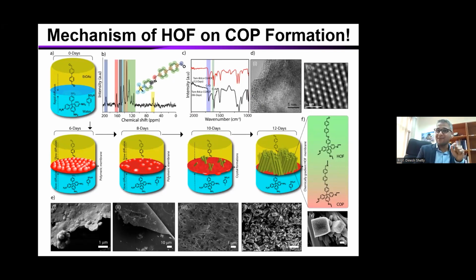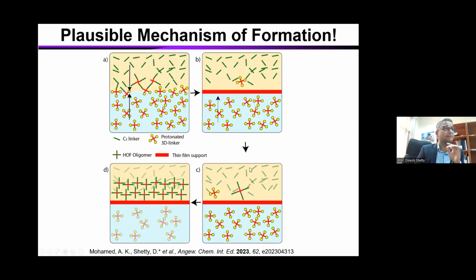But if you think about it, you're talking about the same building block. Usually when we talk about hydrogen bonded networks, right, HOF films, hydrogen bonded organic frameworks, it's very difficult to get them into a film or membrane form. So in this case, we were lucky: first it forms an amorphous film. Over that, the hydrogen bonded organic framework formed. The overall package leads to mechanical stability. We end up getting a very nice freestanding membrane.